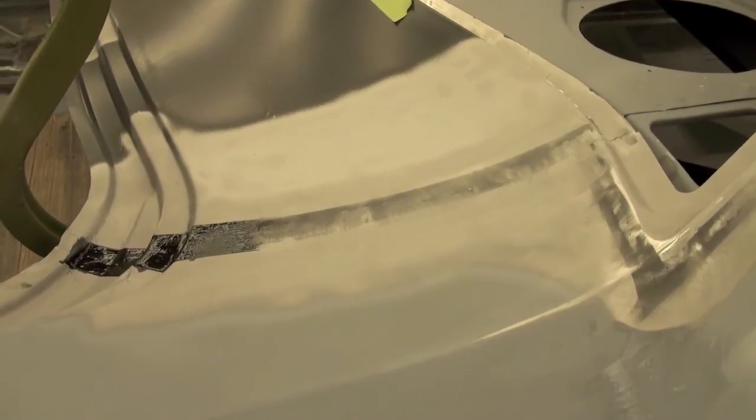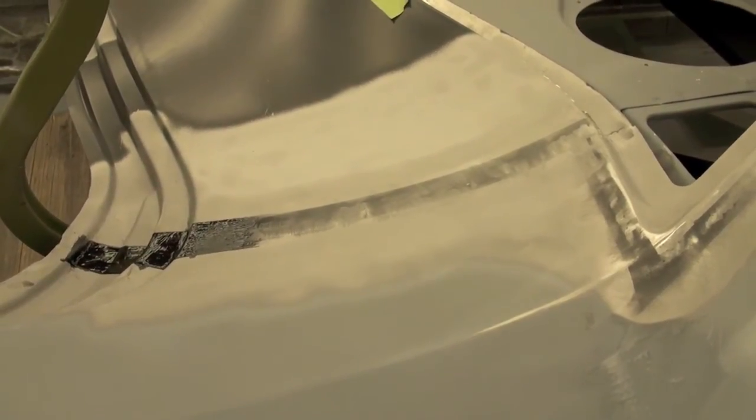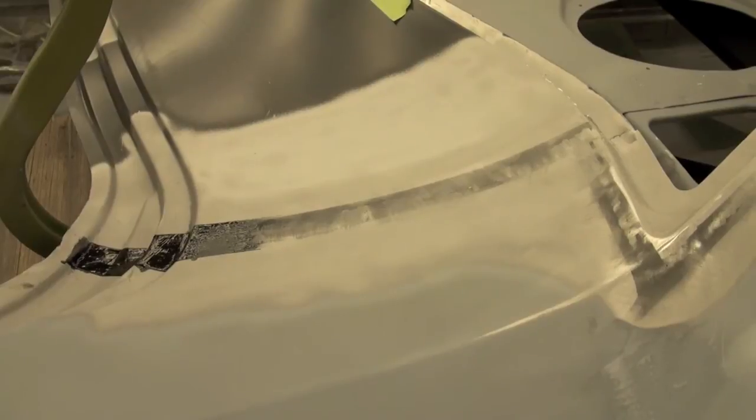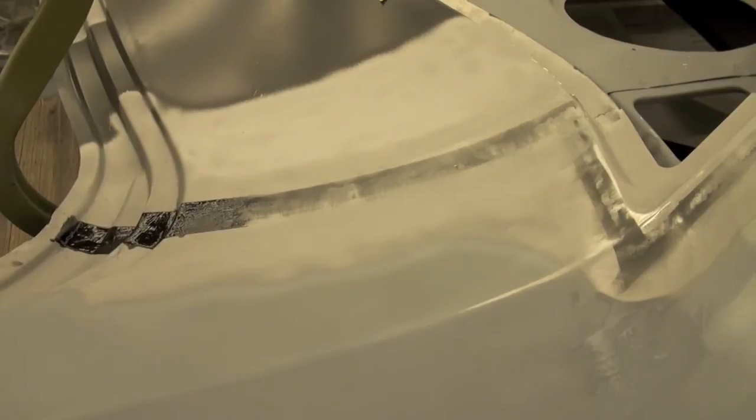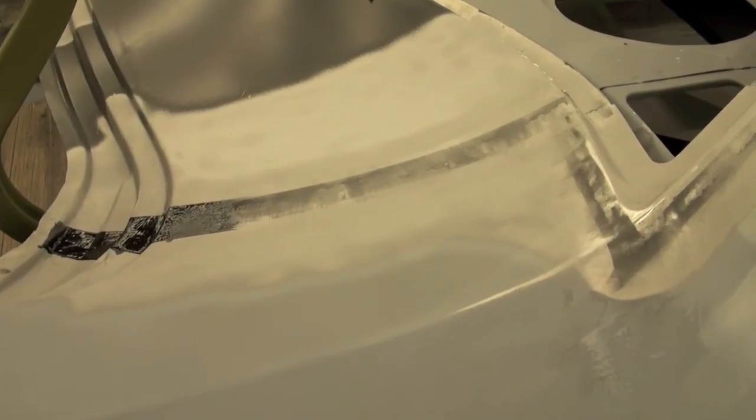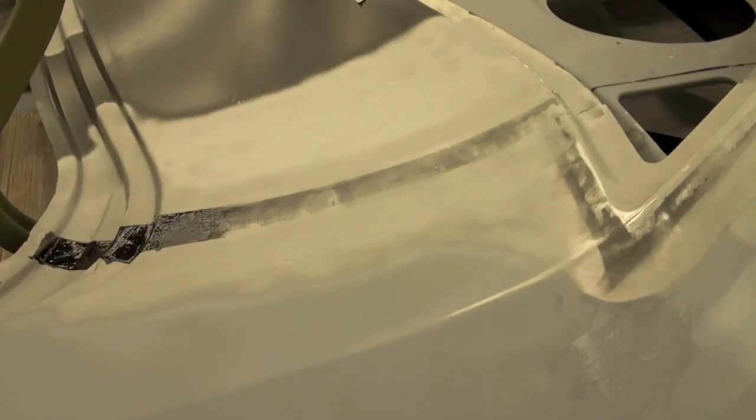I've tested it by building a can and spot welding it and seam sealing it with this material, 3M 8511, and putting water in it for over three months and not a single bubble took place. Most cars aren't going to have water sitting in them for three months, but even a flood car, so it's a pretty good test.